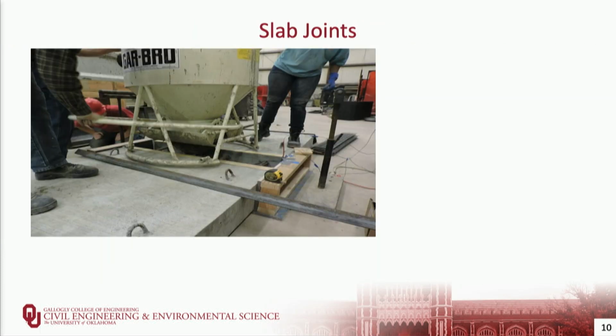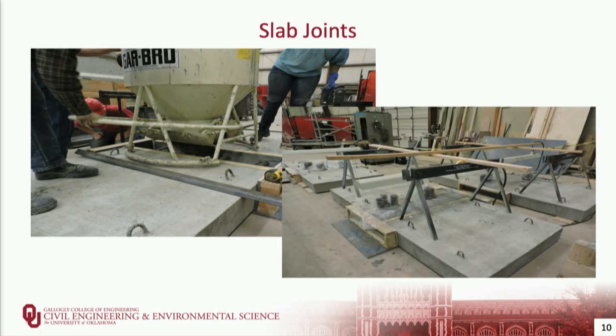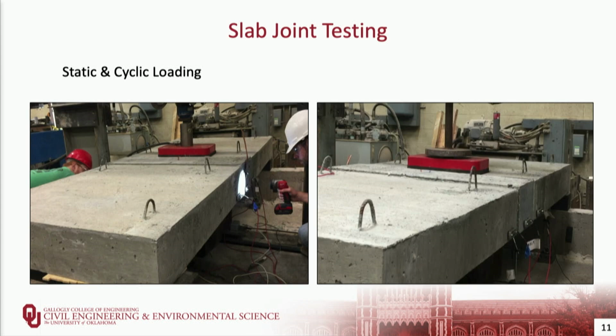To start with, we cast some specimens in our lab at the University of Oklahoma that were similar to these. These were actually intended for repair and retrofit, so it's not exactly the same application, but we tested both the proprietary and non-proprietary UHPC materials. We used contact lap splices for these specimens. We heat cured our UHPC to increase the speed of curing. And then we tested these in both static and cyclic loading.